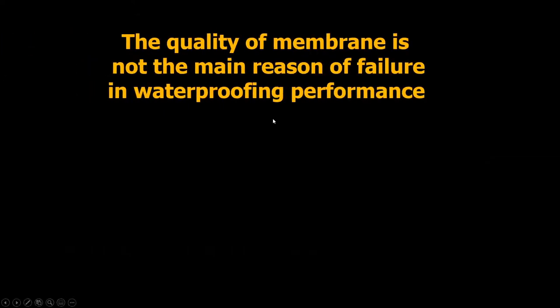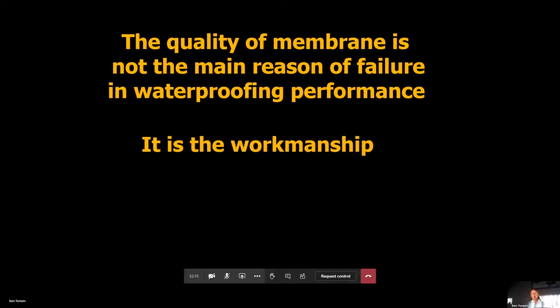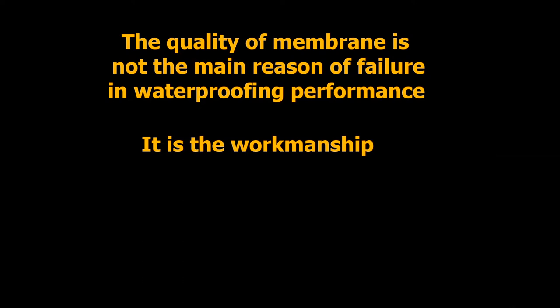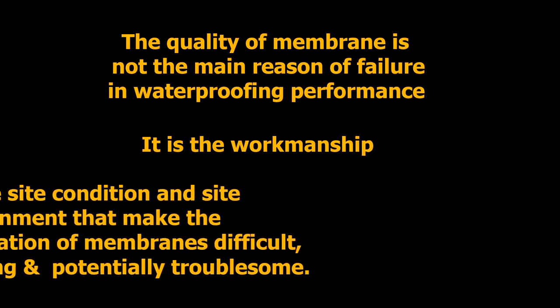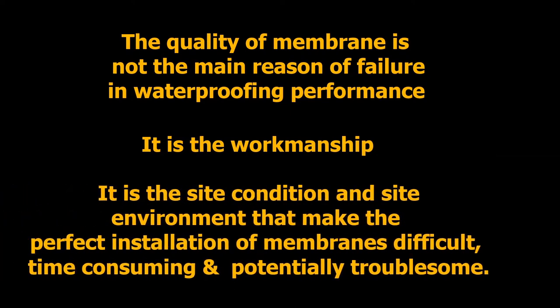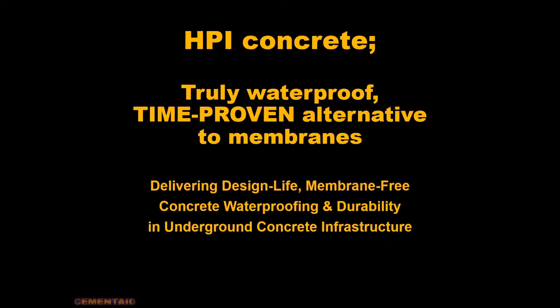And it's not really the fault of the membrane. Membranes these days are pretty good quality. The big problem is the workmanship. Trying to completely wrap a concrete structure up in some sort of membrane is very, very difficult to do without any defects and without any holidays in the membrane. Wherever you've got surface penetrations, very difficult to install and potentially troublesome. So there's got to be an alternative.